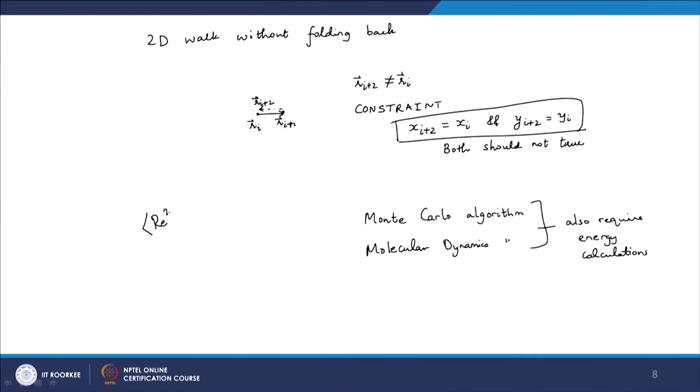We can also establish the scaling law R_e squared proportional to m, and you would see that this would hold for large values of m. This also we can establish from these kinds of small simulations. And finally, once we are in the habit of doing this, the same scheme will go into a more detailed Monte Carlo code, except that we will also have an energy calculation embedded into it. So I want to stop with this.